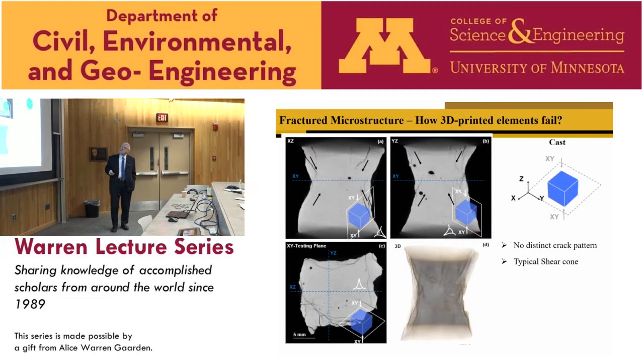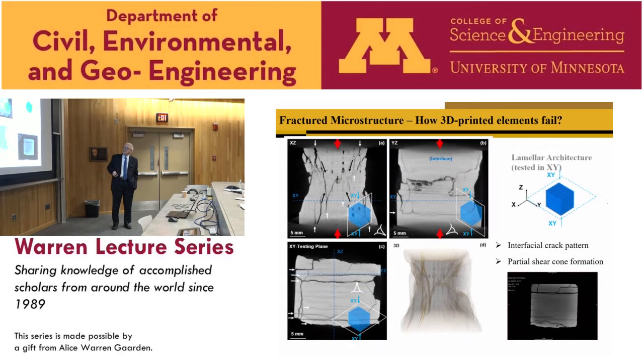If you look at the mode of failure, you can see that for the cast element, so this is the regular cast element, there is no distinct crack pattern. What we get is a failure that looks like a typical shear cone. Normally, there'll be a failure due to the tensile stresses, but because of the restrictions of the platens, we get this confinement. And if you look at the Mohr circle, that actually produces the shear cone type of a stress.